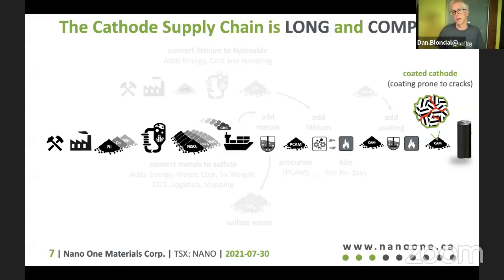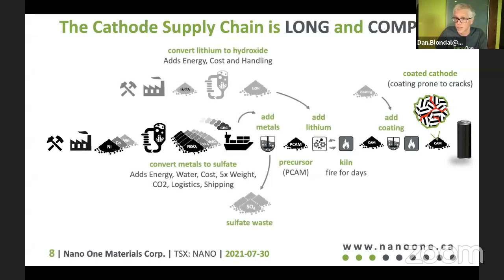These are what we would call a polycrystalline powder. So each little grain of powder consists of a whole bunch of crystals, and the coating goes around that whole bunch of crystals, and it's susceptible to cracking and falling apart as you charge and discharge it in the battery. So a lot of steps. It is long and complex, and what we do differently at Nano One is we